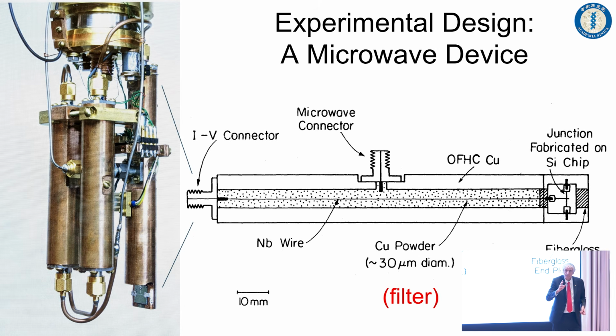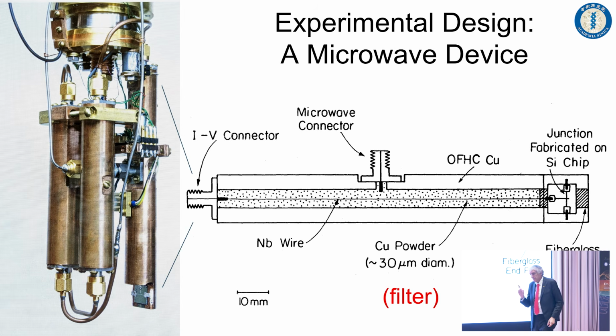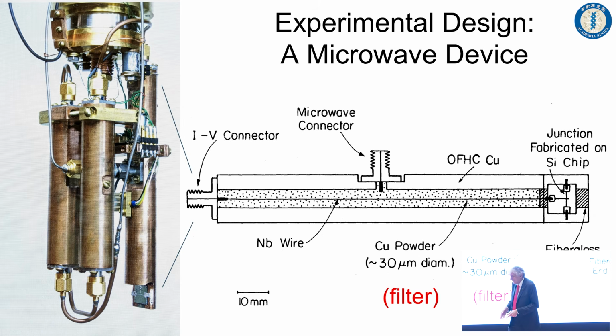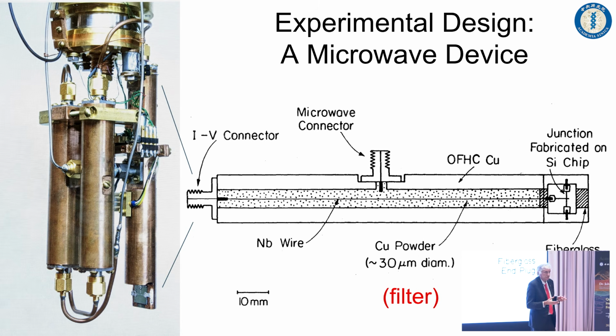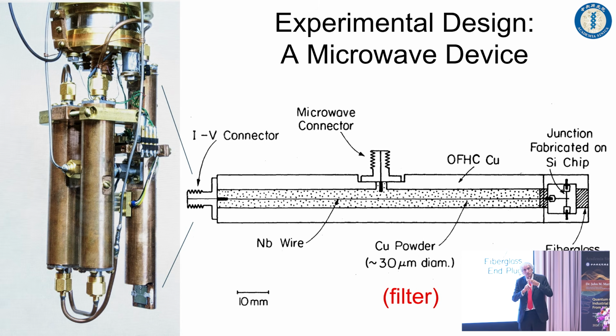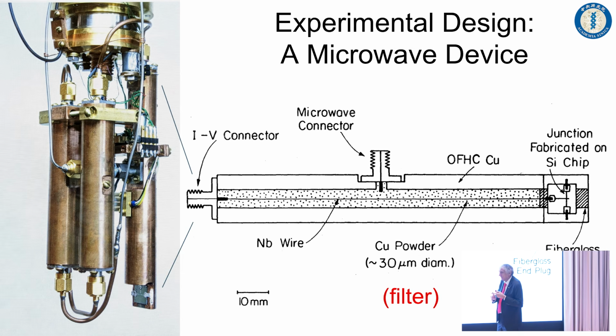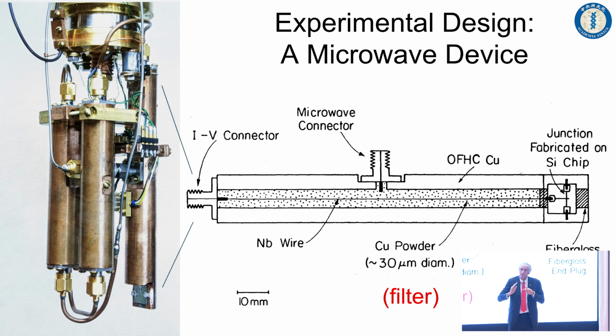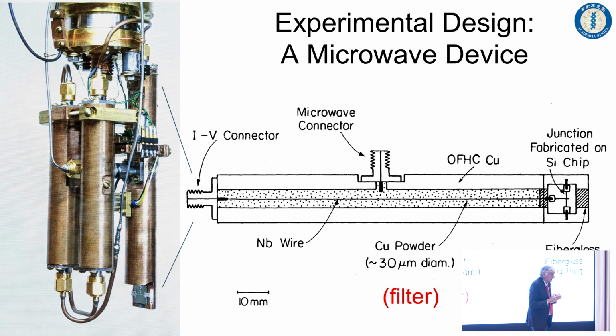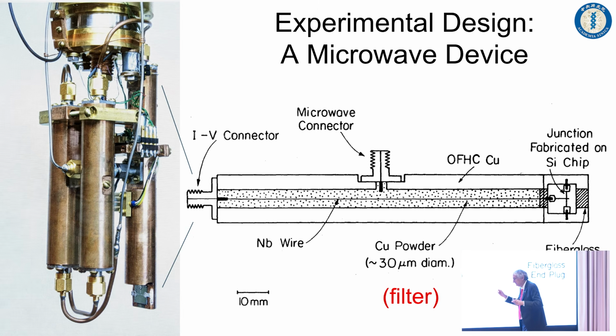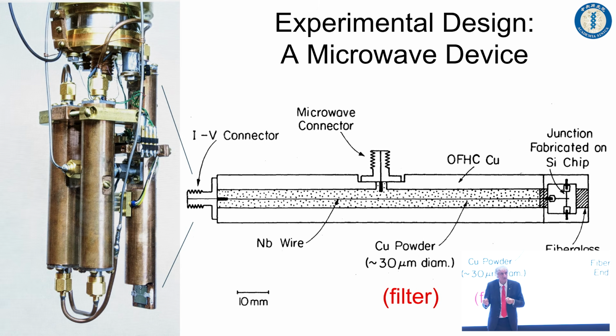Now, the way this experiment works is that we have a superconducting wire, a superconducting Josephson junction, and superconducting behaves such that as you put current through the device, there's 0 voltage across the device. That defines a superconductor. It's a special phase of matter with 0 voltage. However, when you make this tunnel junction, you can only put so much current through the device. If you start putting more current through the device than about 5 or 10 microamps, if it's designed carefully, then it's no longer going to look like a superconductor. It kind of breaks the superconductivity, and you see a voltage appear across the device.